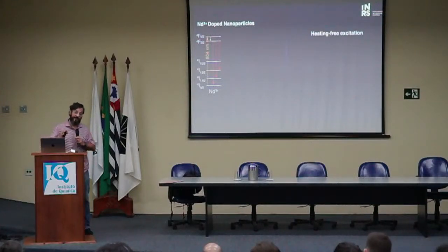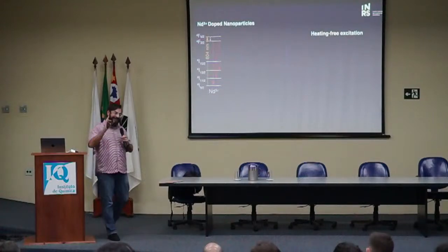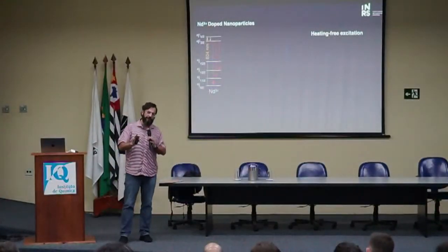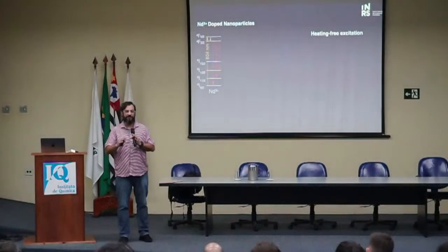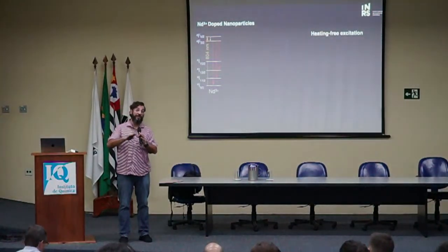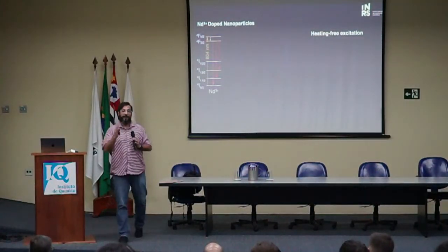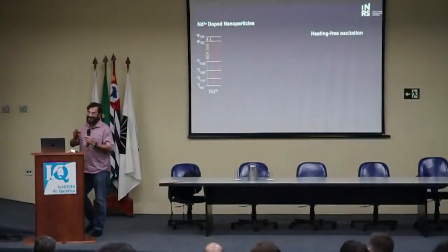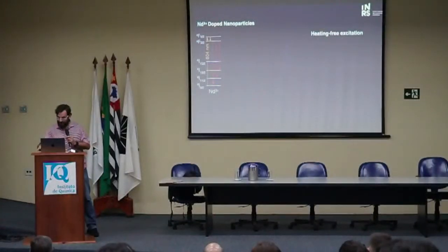800 is a heating-free excitation. I forgot to mention that we use 980 typically for upconversion. 980 heats, okay? It's absorbed by water. So we need to take that into consideration when we're doing our experiments. We don't have that problem with 800, or at least it's much, much less drastic. So we consider it a heating-free wavelength.